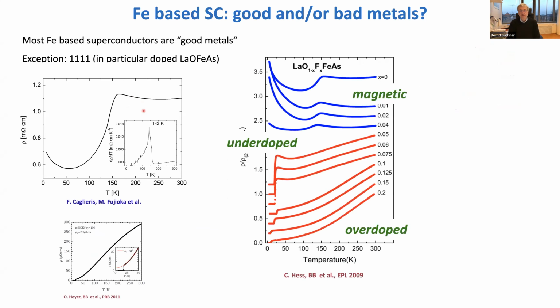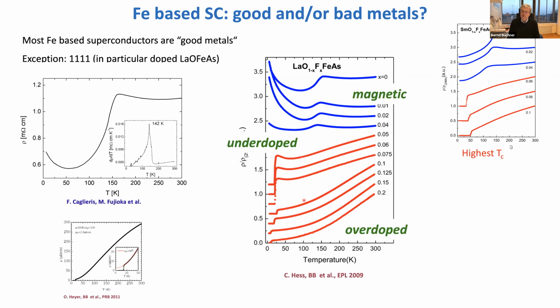And that's also what you see as a function of doping. This is very early data where you see that when you leave this magnetic phase, you still have, in the so-called underdoped region, this tendency to localization. Only if you go to very high doping concentrations, you end up with a resistivity which qualitatively looks like what we know from these very nice metallic systems. Okay, and this is, I think, important because at the end of the day, these 1111 type systems show the highest TC in the bulk iron-based superconductors, 50 or 60 Kelvin. So a factor of 2 larger than what you observe in all these metallic systems. Therefore, I think it's interesting to have a closer look at the materials, to see what is really determining these very strange, unusual normal state properties